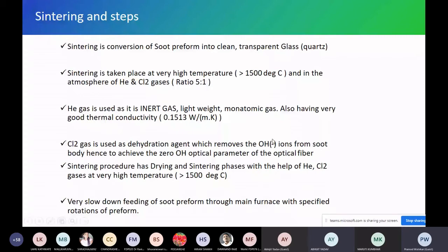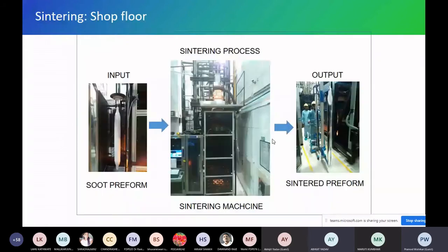Okay, so here are some photographs that we want to show. This is the soot here. We put the soot into the furnace. This is our furnace here, and it's going inside. It's heating here in the sintering machine, and once done, this white rod becomes transparent glass. We call it a preform, a sintered preform. So that is the step here.